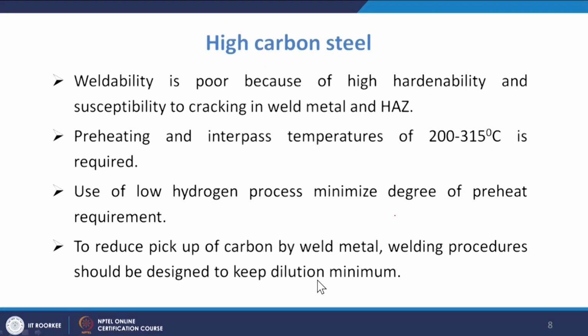So use of low hydrogen practice minimizes the degree of preheat requirement. To reduce the pickup of carbon by the weld metal, the welding procedure should be designed to keep the dilution minimum. Generally if the dilution is more, more carbon can be picked up from the base material and HAZ into the weld material. So to minimize that, the weld procedure should be designed so that weld dilution is minimum.